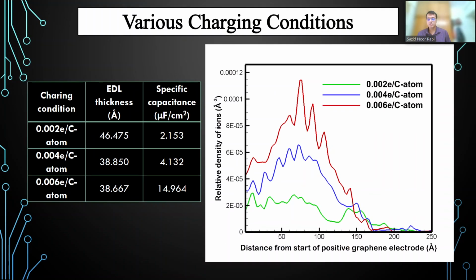We have used different charging conditions to see the effect on specific capacitance. We can see that it has a very profound effect on the specific capacitance. However, the EDL thickness doesn't change much due to the charging condition changes.